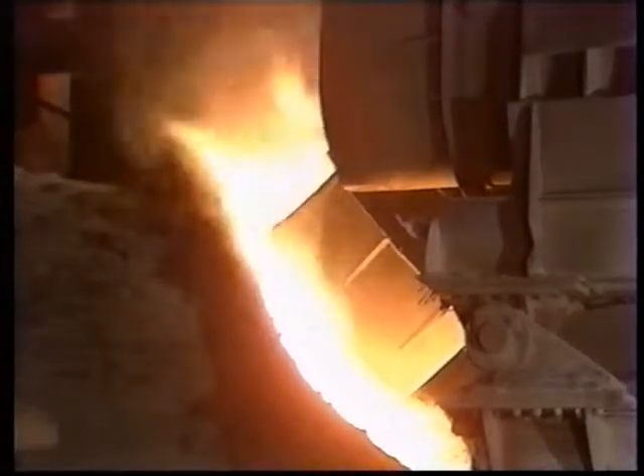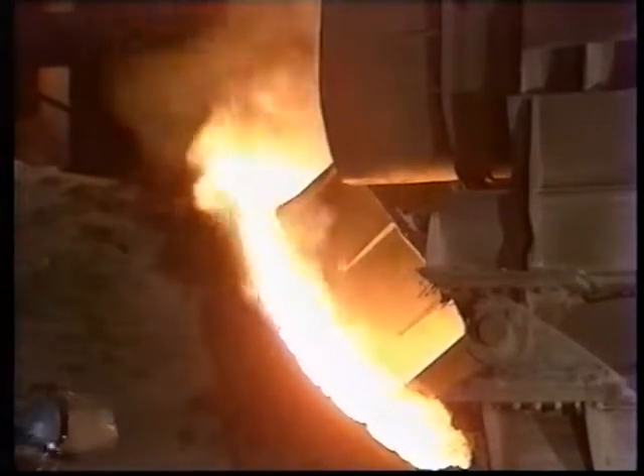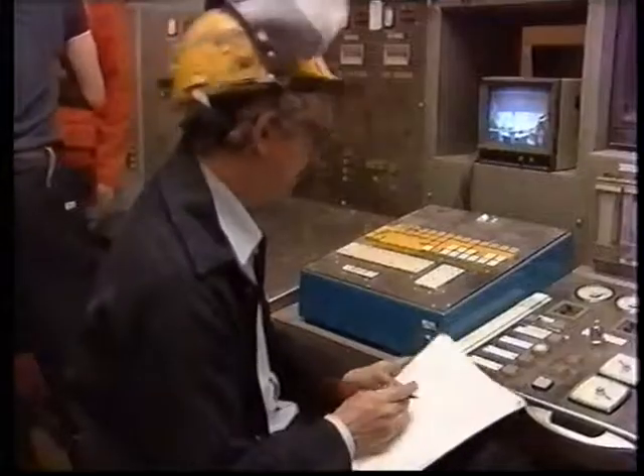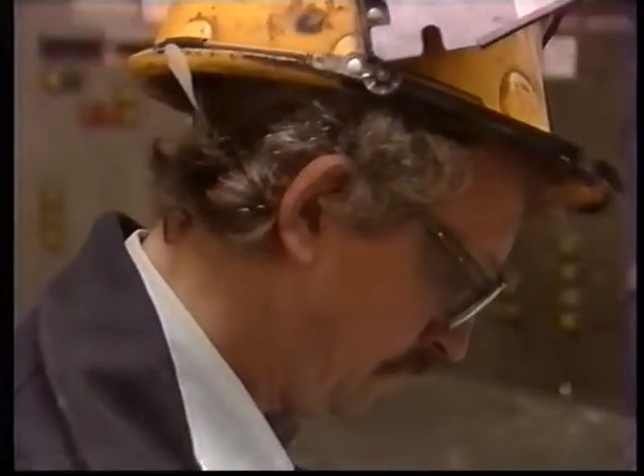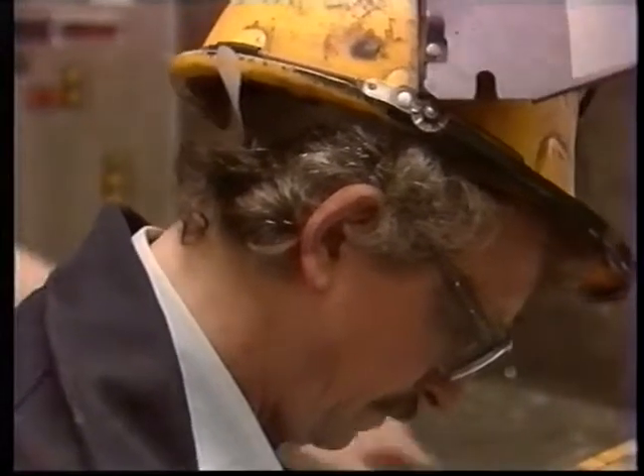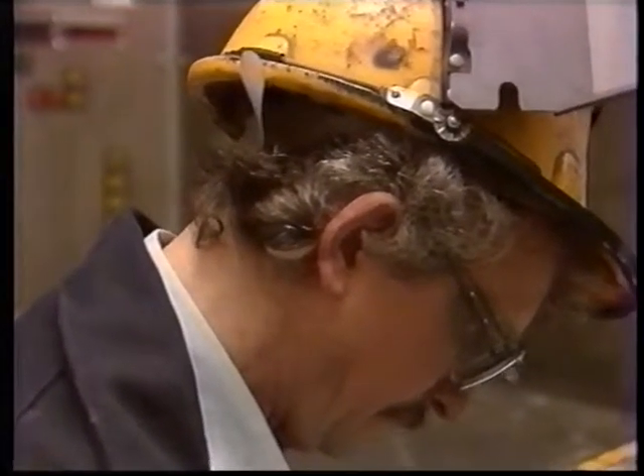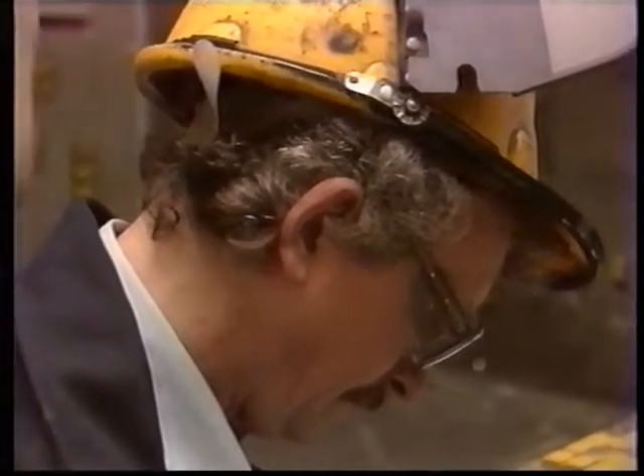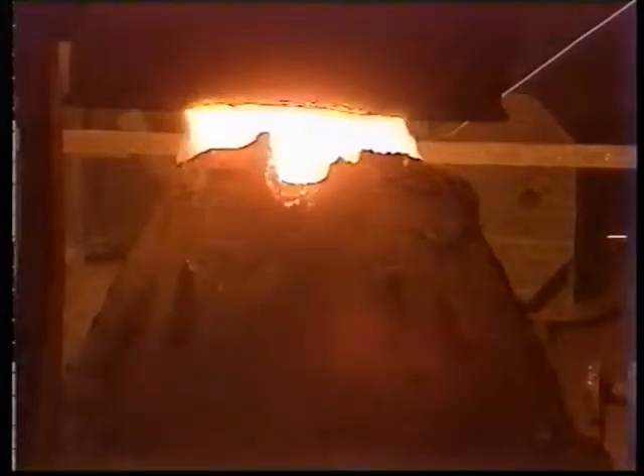Once we get down to the required carbon level, we add a reduction mix to reduce the oxides in the slag back into their metallic forms. Afterwards, we add a desulfurizing mix to further reduce the sulfur level and then make small trim additions to meet the final specification.